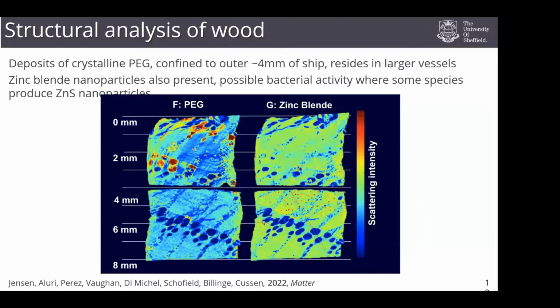That's really useful because, unfortunately, polyethylene glycol can break down over time to form acids itself. And so this is now a new conservation challenge that people are facing, to try to locate whereabouts that polyethylene glycol may be breaking down. And experiments like this are pointing people in the direction of areas where they might want to focus in on the ship.